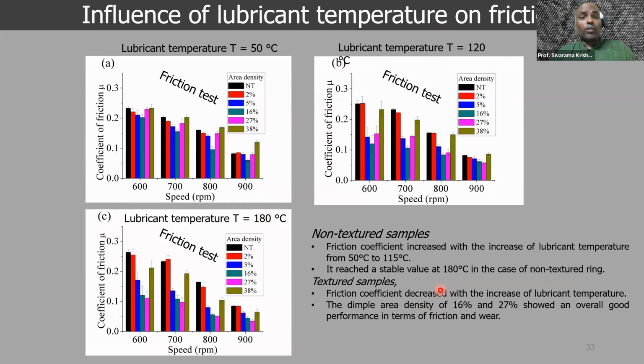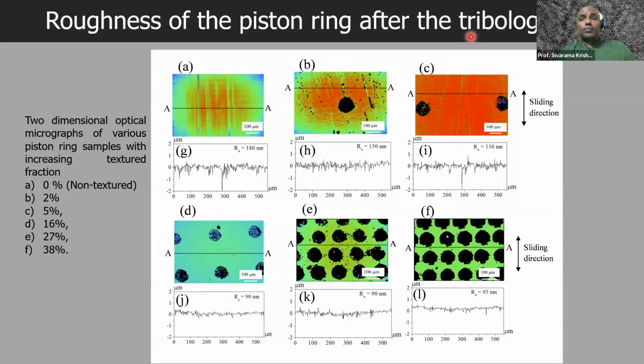Therefore, we sort of rest the case that this kind of texturing with very low thermal burden and debris is indeed a very nice idea. And here we also measured using non-contact optical profilometry, got a direct measure of the roughness of the surfaces, especially the used surfaces after the test.